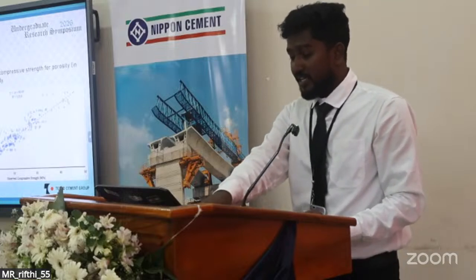Then after that we choose aggregate size and shape also. With that we predict the compressive strength. Here we change the equation constants A and F. From that we predict the compressive strength, and from that we plot observed and predicted. From that we get the accuracy of 0.92.